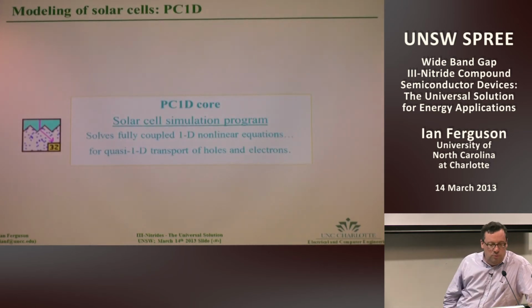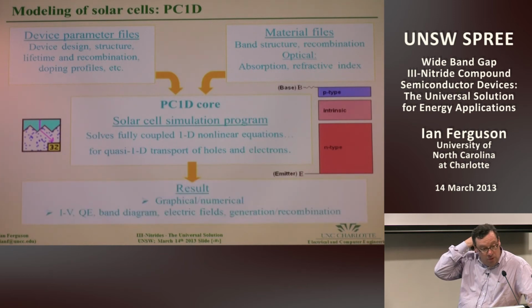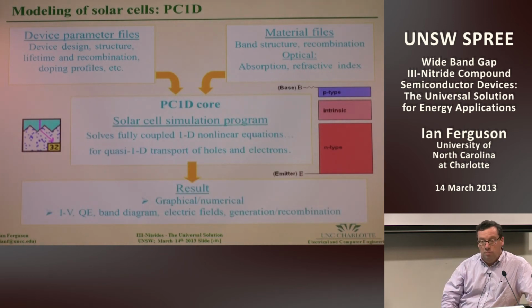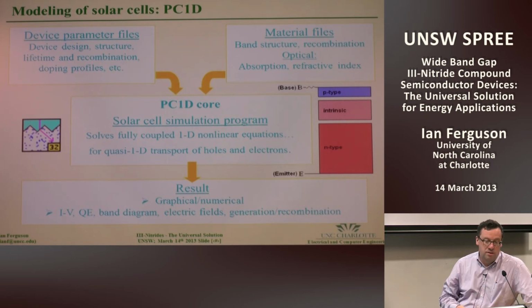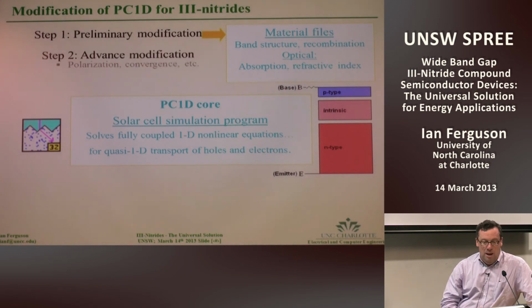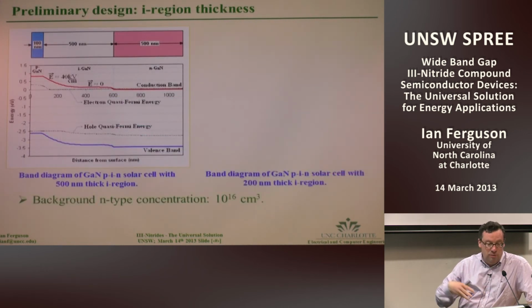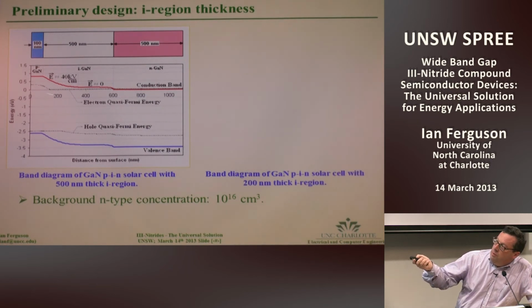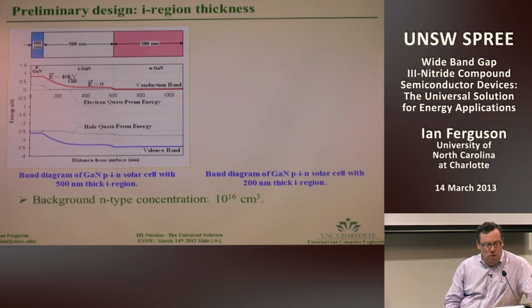So what we did was we took the PC1C and PC1D core programs, and then we had to build materials files for these new materials. Then we had to go back in and modify the code so we could put in these polarization effects within the materials as well. I'll show you some issues with just absorption and some other things that we had to address. If you look at preliminary designs, you can see here our depletion region is only about 0.2 microns. And we could run this in other codes as well.